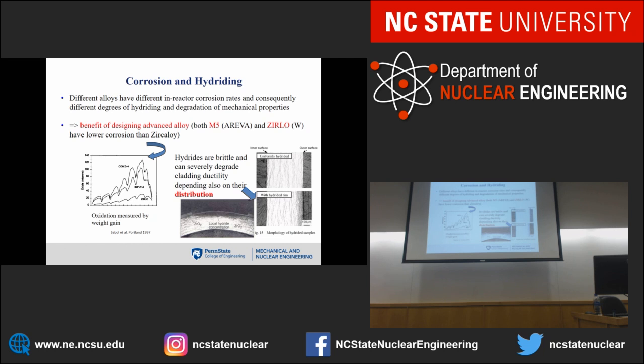So the oxide layer is actually an insulating layer, and therefore the temperature here is colder than the temperature here, so the hydrogen just precipitates there and forms a blister. Now imagine that I'm trying to put a hoop stress in here. This would crack very, very early, and all the failure would concentrate here, at a very small strain. So that's the kind of thing that we're worried about, the distribution of the hydrogen.